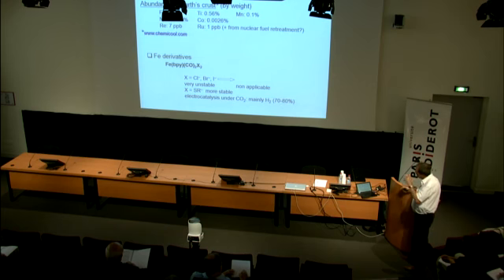So we shifted to try to make some more stable compound by replacing the anionic ligand by a stronger one, for instance, a thiol derivative. Complexes are very much stable, but electrocatalysis under CO2 gives mainly hydrogen. It's a good catalyst for hydrogen production, but not for reduction of CO2. What does it mean? That means that probably the reduction of CO2 doesn't go through the formation of a hydride.